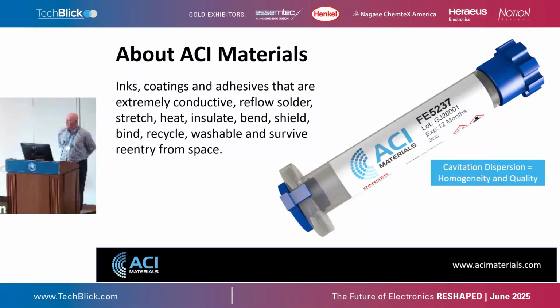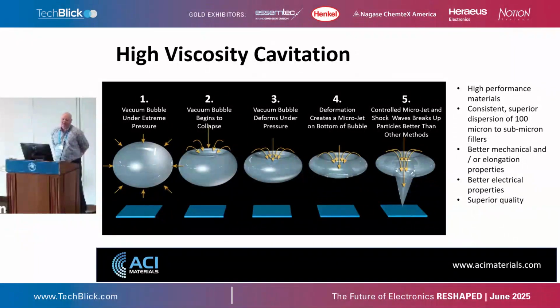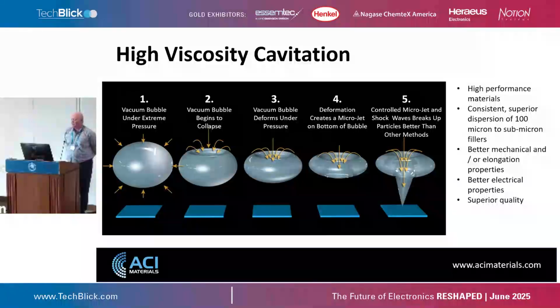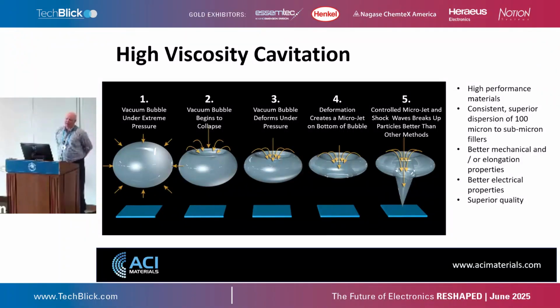And the key to ACI's manufacturing is in their cavitation, high viscosity cavitation dispersion. I've been in the coatings and inks business for a long time, and there are a lot of very traditional ways to manufacture coatings, three-roll milling, bead milling, etc. This is really a new way to disperse metallic and even pigments, carbon nanotubes, graphene very, very efficiently and evenly. If any of you know much about these particles, they often come agglomerated, and to really get the best performance out of them, you need to break up agglomerates and disperse them very, very evenly throughout the coating or the ink, the conductive ink or whatever, to get the best performance.